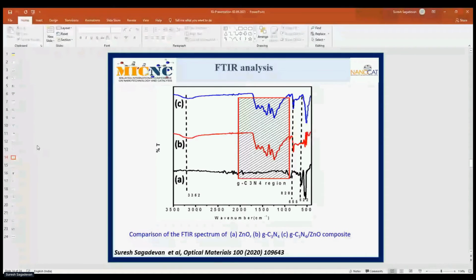In addition, we observed the band at 522 cm⁻¹, which confirms the zinc-oxygen bonding, which means the presence of zinc oxide in the composite sample is linked to the Zn-O stretching vibration. Also, the wide band in the range of 2750 to 3500 can be due to the OH stretching vibration from absorbed water or moisture. So from this FTIR analysis, we conclude that it provides information about the matching of zinc oxide and graphitic carbon nitride peaks, which means the successful formation of the graphitic carbon nitride and zinc oxide composite. Once again, we confirm this using FTIR analysis.